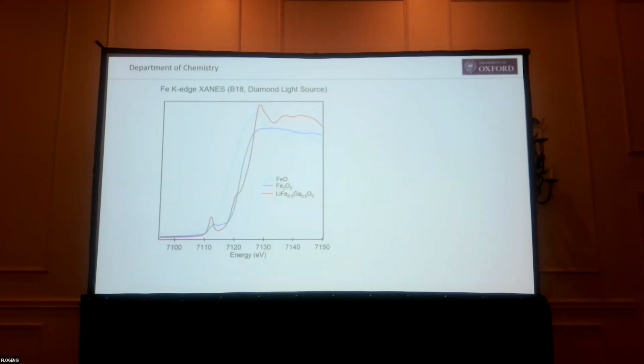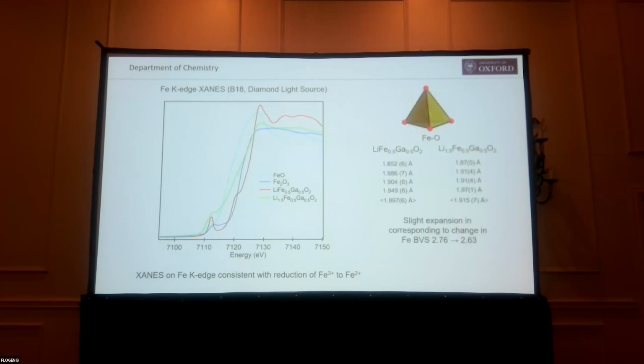So you see this would be an iron ion. And we can check that the iron is being reduced by doing some absorption measurements. So this is XANES data. What I'm showing here in the red is the iron K-edge for the iron gallium material before we lithiated. We've got two standards here for iron 2 and iron 3. And post lithiation, we can see that this edge moves to lower energy, consistent with reduction. And if we look at the bond lengths of the system, they get longer, consistent with reduction. So it looks pretty good that we can reduce this system by lithium insertion.